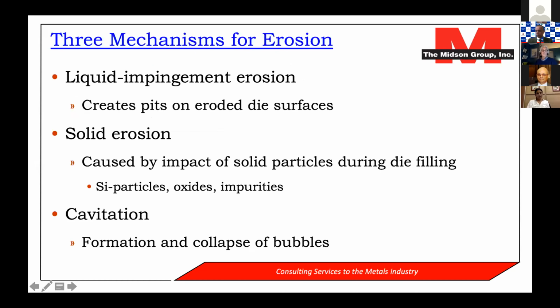And so there's basically 3 mechanisms for erosion. We have liquid impingement erosion. This is when the liquid aluminum, for example, is at a very high velocity around the gate, or maybe impinging directly on a core very close to the gate. And basically the steel die is dissolved by the liquid aluminum.